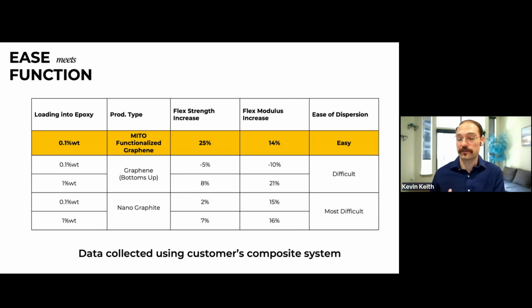And most customers that I talk to, they have tried graphene or they've heard horror stories of graphene. And whenever people have tried graphene, I would say probably 99% of the time, they've been burned by it. Most people, they've spent millions of dollars, a lot of time and effort trying to source and qualify graphene. And even then, that 1% that gets it over the line, most of the time they have a feedstock issue. So when you're able to formulate on top of the graphene material and you understand the buckets that you need to fill, you can start supplementing that one supplier, and you're able to branch out and make 2-3 different suppliers fit within your range of what you really need.